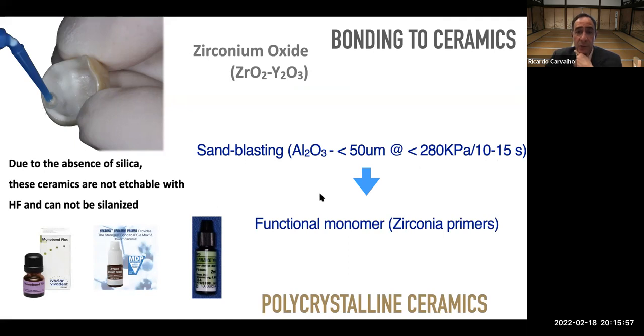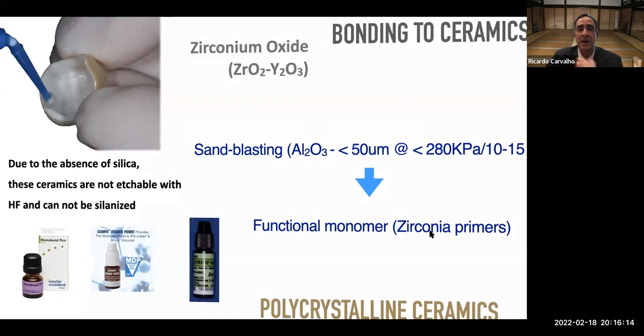But what is probably most important, if you will, when bonding to zirconia, instead of using silane, we have what is called functional monomers, or zirconia primers, commercially available nowadays. These are MDP-based materials that offer chemical adhesion to zirconia, albeit a very weak chemical adhesion, much weaker than the covalent bond we obtain with glass ceramics, but still a recognized bond that we should always be able to accomplish in order to secure the cementation of zirconia crowns.